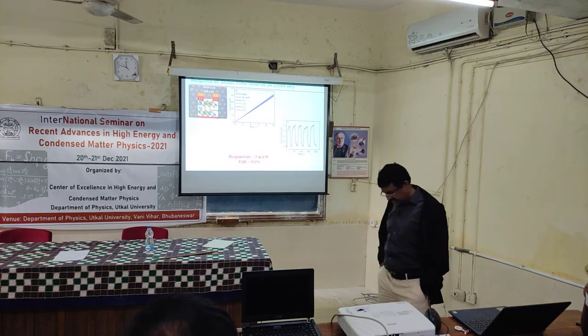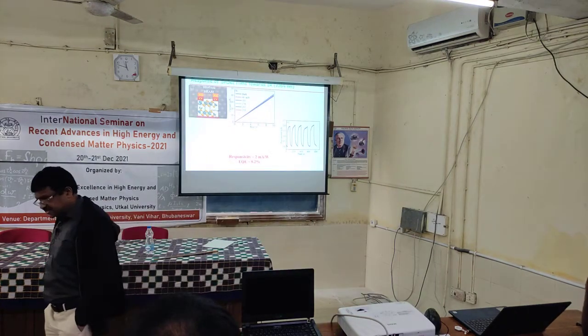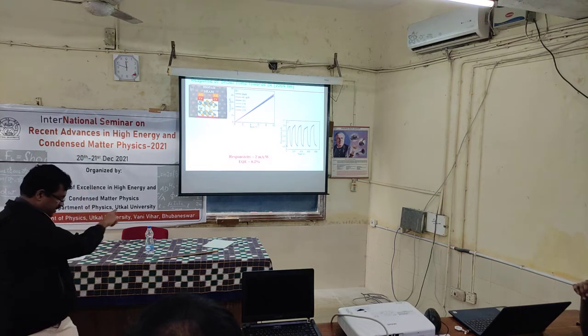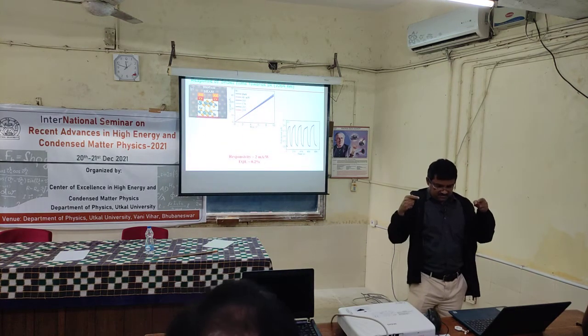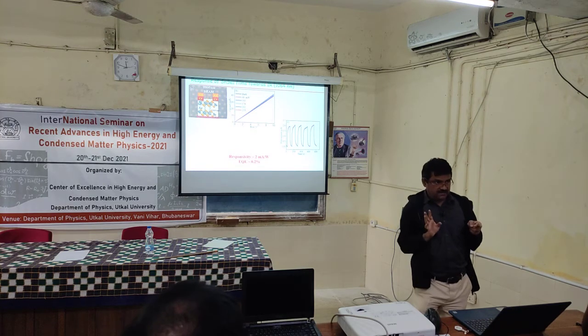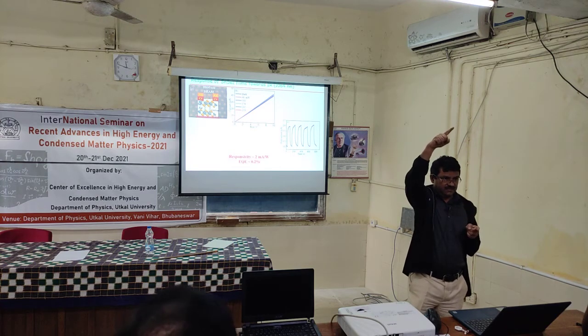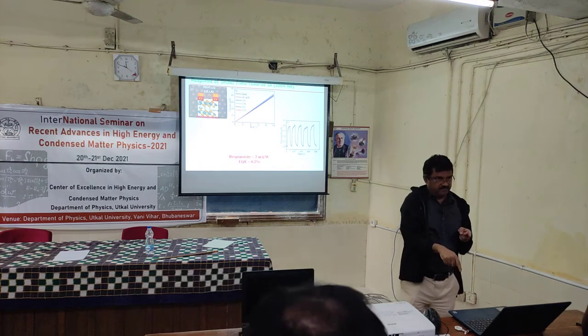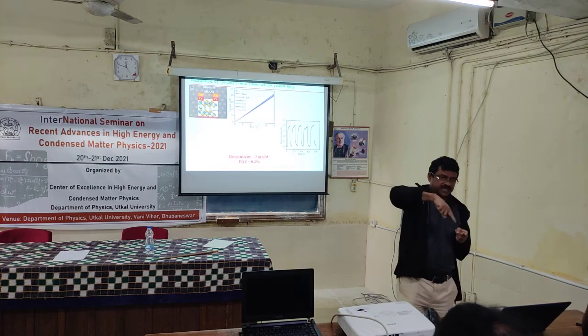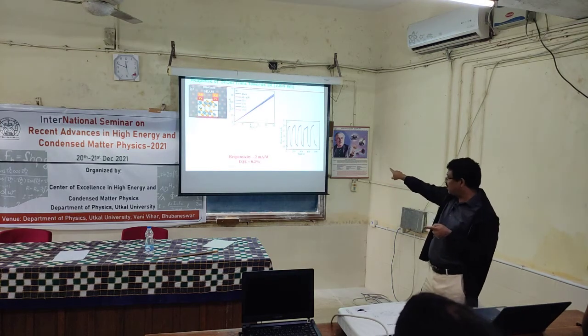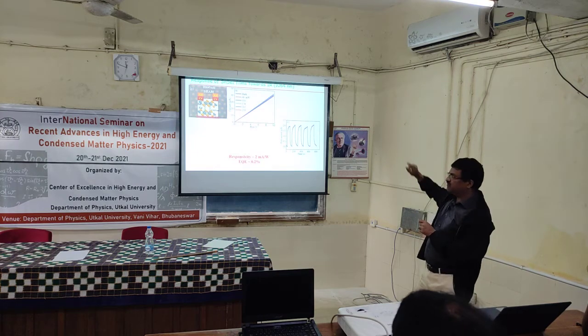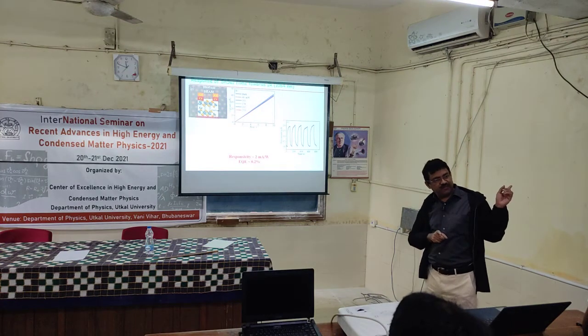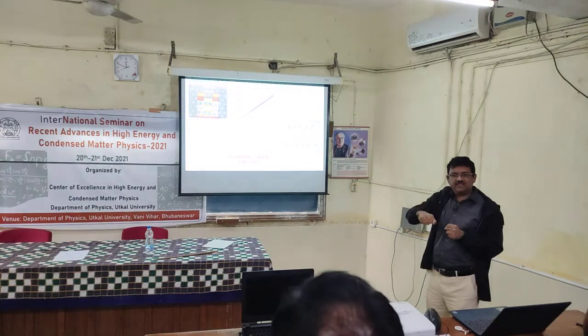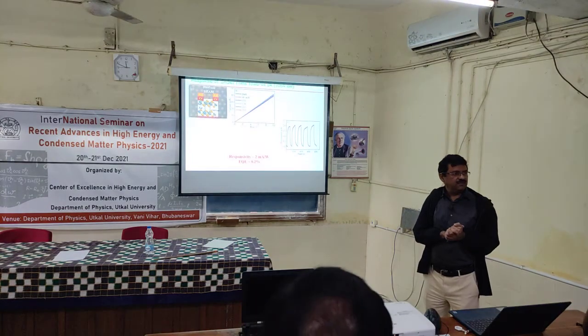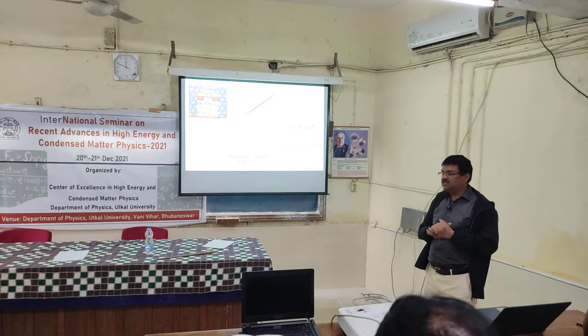This is the typical curve generally obtained for either photodetection or gas sensing. It is called the temporal response curve, the photocurrent versus time. What is done is you take your device, apply bias, and measure the dark current. Now you shine the light, there is an increase in the current, and then you take it out, and there is a drop again. Now you shine again, it increases again, switch off, like that. That is basically called the on-off curve or temporal response curve, and it shows how fast your device is responding. That is related to your transit time or the response time. And once you turn off the light, how fast does it come back to the dark current.